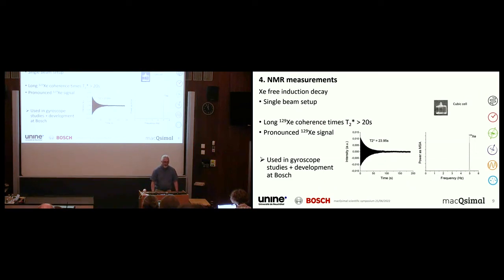Now looking at NMR measurements, here are some first results that were realized by the Bosch team in Germany. And they show us the xenon free induction decay in a gyroscope setup using a single beam only and no RF drive. After the polarization, we can see here a ringdown of the signal detected via the rubidium laser interaction, as described before. And we get a very long relaxation time, T2*, of this xenon spin of 20 seconds, and that's very helpful in order to do the gyroscope developments.